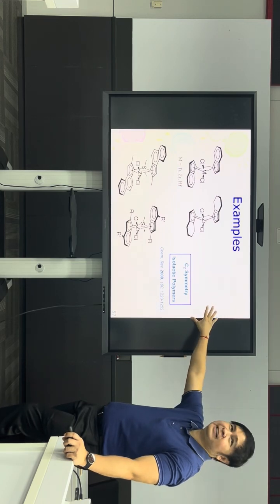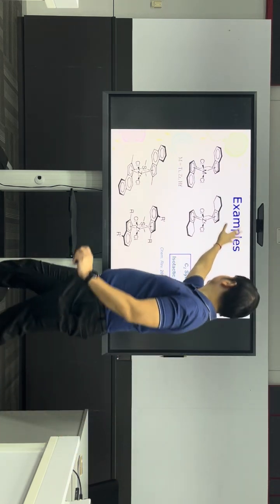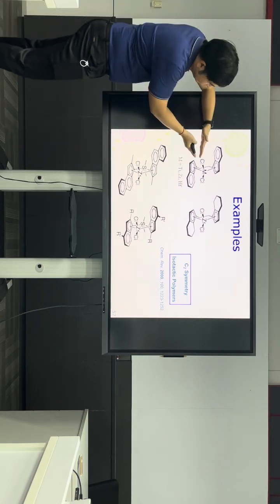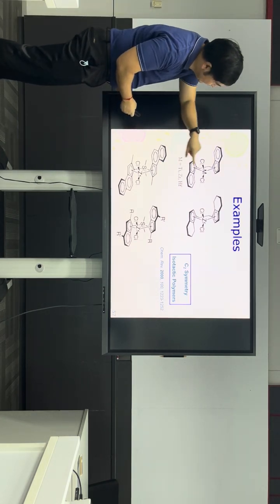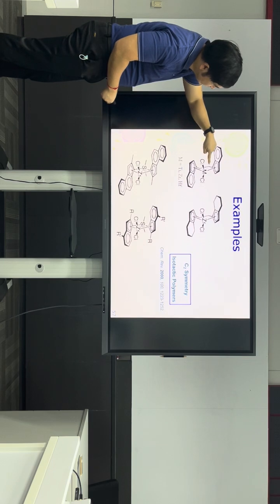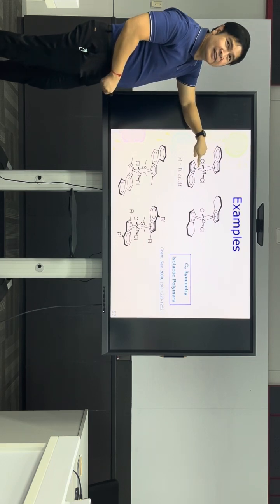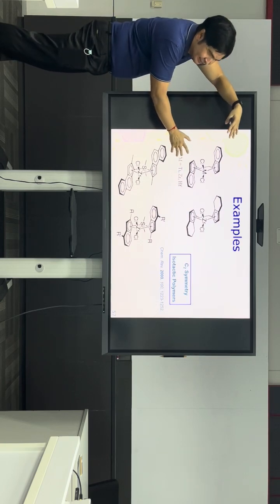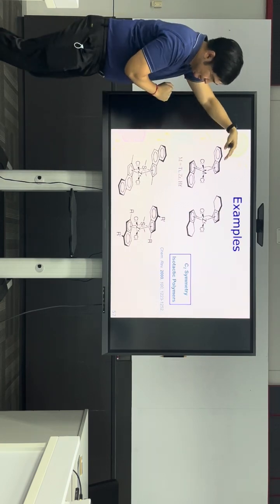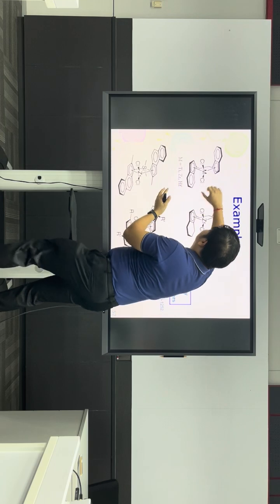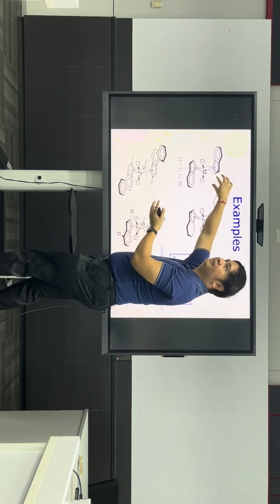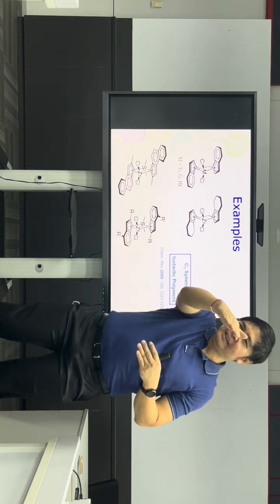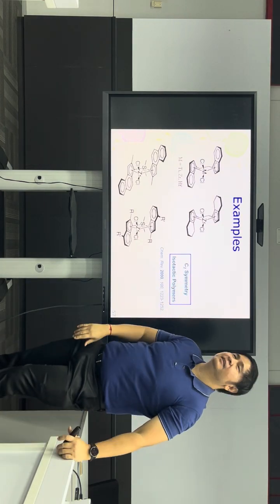Let's take a look at a real example then. You see, this is isotactic polymer. From this side, you approach at this angle. The two Cp rings are linked by CH2. Okay, and you approach this side. Right hand side is empty, right? Right hand side here is good. If you approach here, still right hand side is good. So it will be the same. Up, up, up, up, or it can be down, down, down, down. It's the same thing, right?